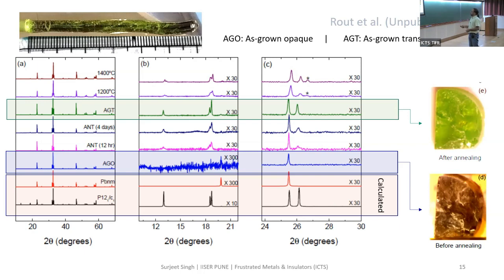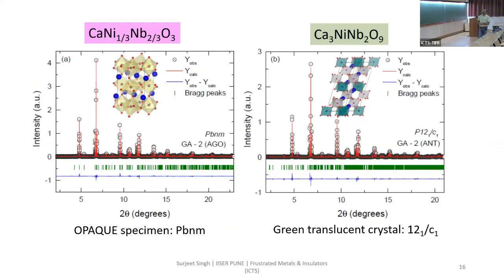So in the lower panel, we have the calculated XRD pattern for two different symmetries. This is the monoclinic symmetry, which is an ordered structure, B-site ordered, where niobium and nickel are ordered, and the ordering is 1:2 ordering. And then the other one is the structure where the B site is occupied by niobium and nickel randomly. And this is the calculated XRD pattern. And you see that the black specimen agrees very nicely with the red curve over here, which is for the Pbnm, the orthorhombic symmetry, because of this missing peak over here. On the other hand, the green specimen is an ordered structure where you have this peak. So the difference is because of the crystal structure difference and not because of any measurable oxygen off-stoichiometry.